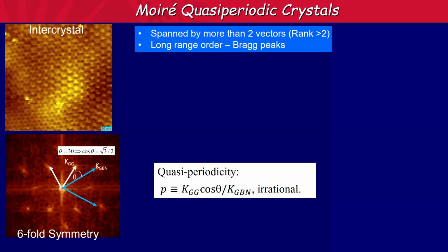So here is an example of an intercrystal. This is the topography, and this is the Fourier transform. You see the blue lines are the reciprocal lattice vectors of the GBN, and the blue one of the GG. In this particular one, the GG is at 30 degrees to the GBN. For quasi-periodicity, the projection of one of the vectors on the other has to be irrational. Obviously, in this particular case, theta is 30 degrees, so we have an irrational projection.